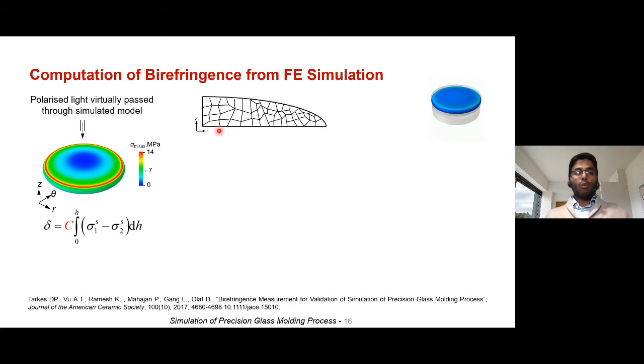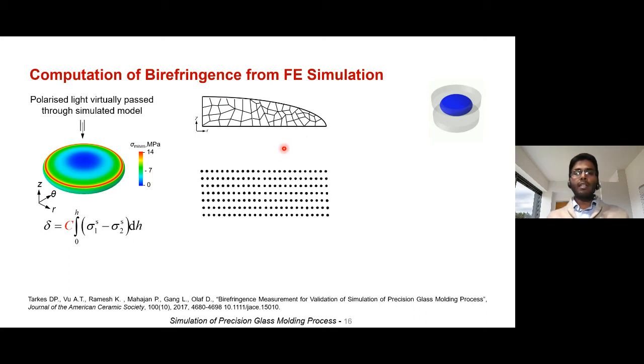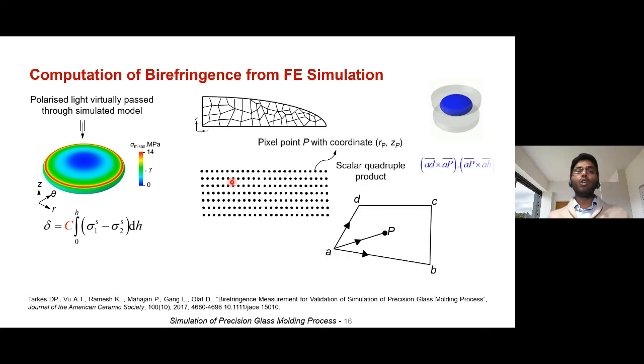So in order to convert into birefringence data, this is the equation that we have. It is the photoelastic constant multiplied by the secondary principal stress difference, integrated over the thickness through which the light rays pass. Here, this is the axisymmetric model, and virtually I have to pass the light rays through this domain and through this thickness, and I have to compute the birefringence. But we already know that light rays travel in a straight line. That means the stress information has to lie in a straight line in order to do this integration operation. So what I did is I introduced an artificial pixelated image, and I tried to find out which of these pixels lie within the domain of the lens.